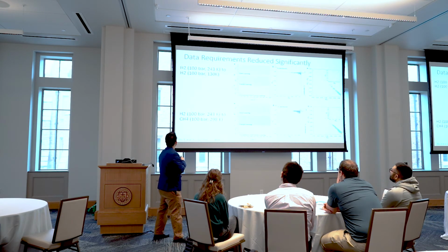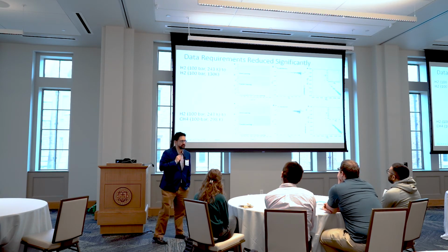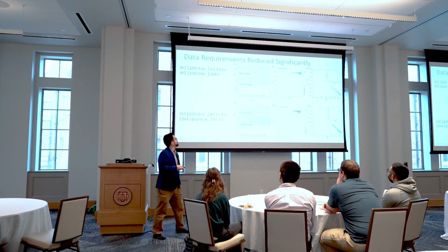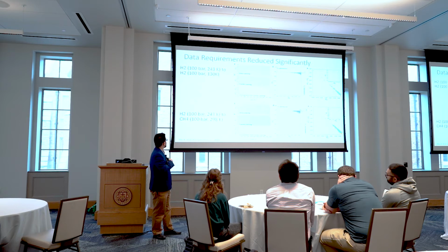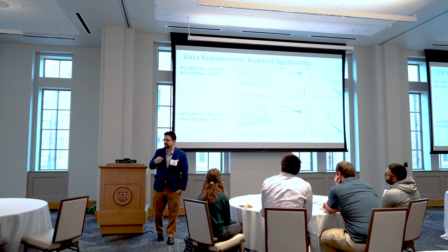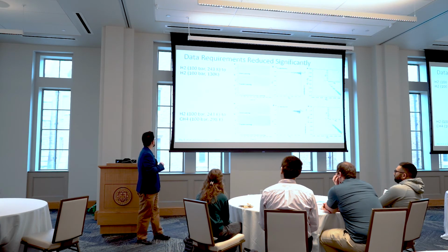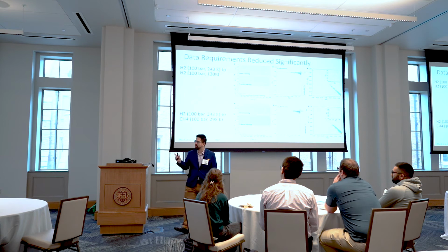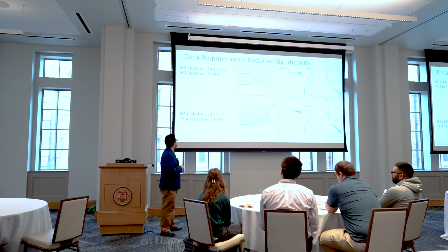Okay, so we were able to do it, say, for hydrogen at one temperature and pressure. We were able to transfer that knowledge to a different temperature. So maybe this is something you want to do, since changing temperatures in your equipment might be difficult. We can get great agreement there. And then beyond just temperature, transferring knowledge to a different adsorbate altogether. So now we go from hydrogen to methane, so it's a different structure, different chemistry altogether. We are able to also do that knowledge transfer, again just training that model with 100 data points, just doing that last layer, and we're still able to get very good agreement, okay?